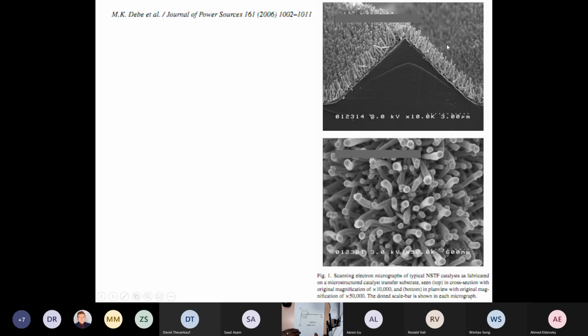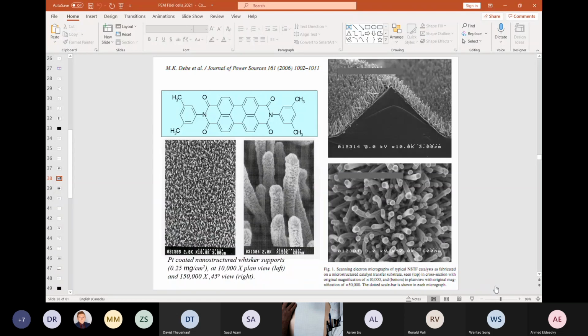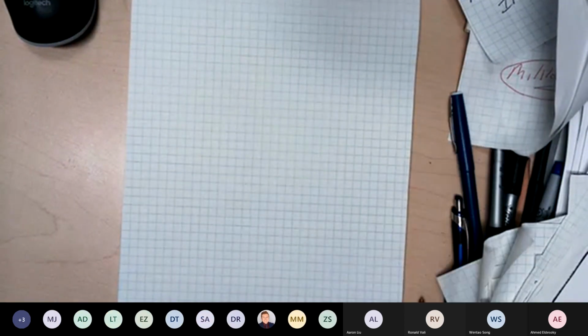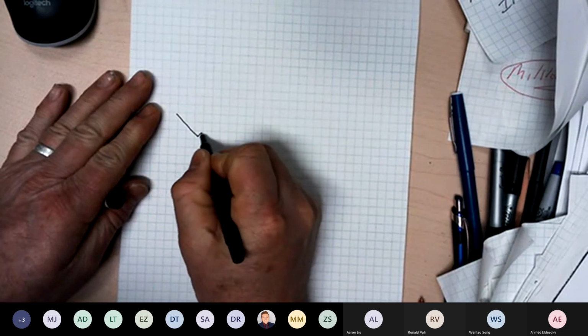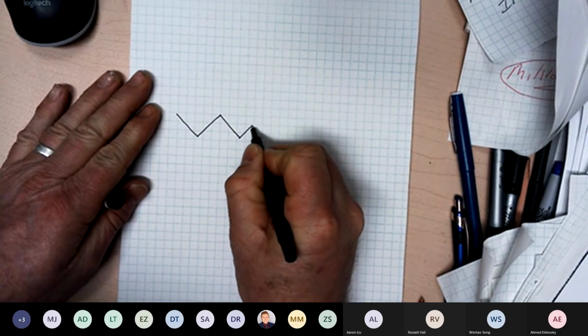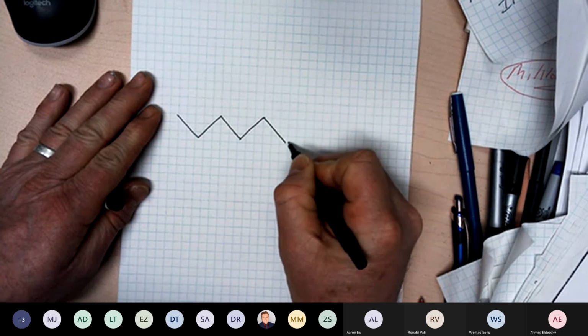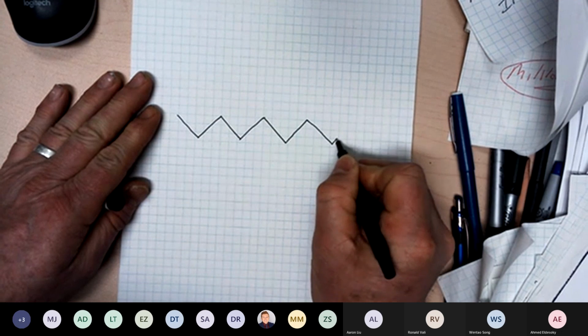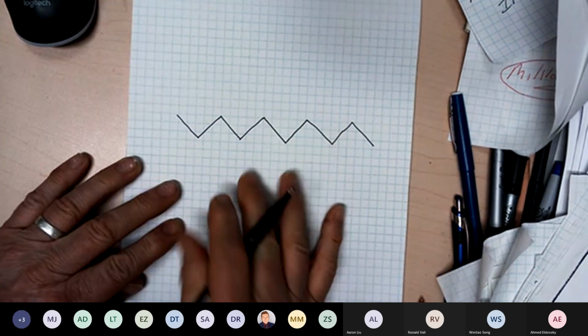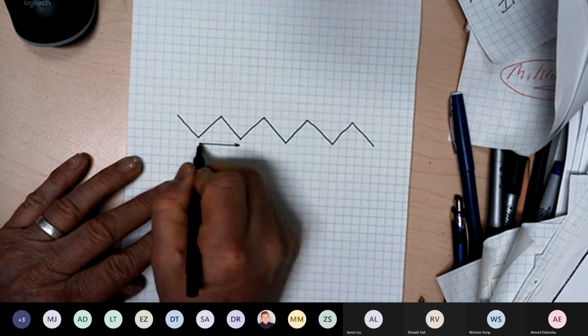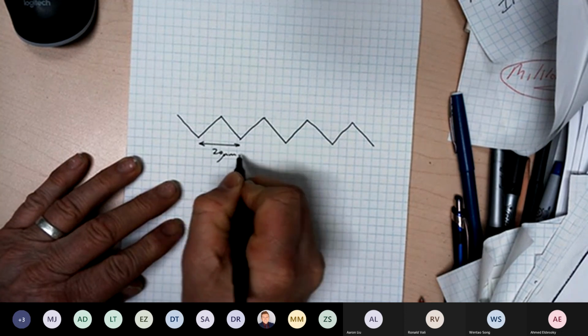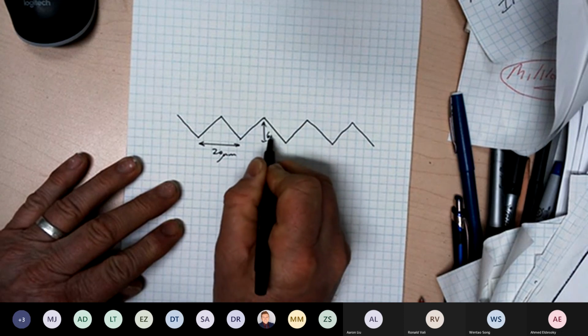I'm going to draw you a picture on my document camera because I want to make it clear. And this is a top-down view of the whiskers here, okay? So I'm going to switch to my document camera for a second. You should see the camera. So what they did is they took polyimide, it's a plastic. It was not very thick, maybe 20 micron thick plastic film. And they made this triangular structure where this was about 20 microns, and this was about 6 microns.